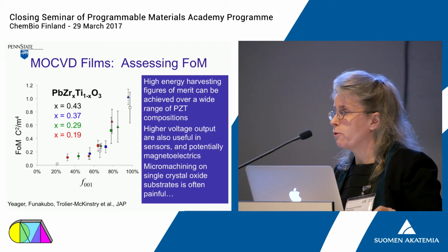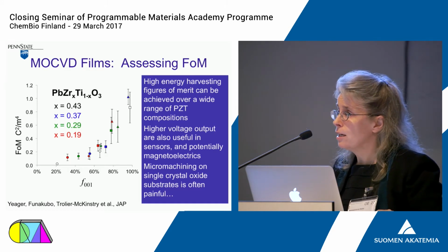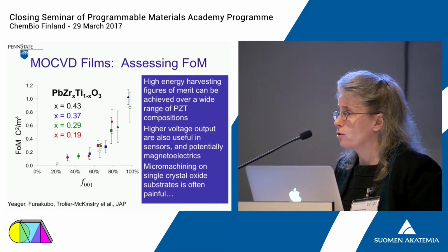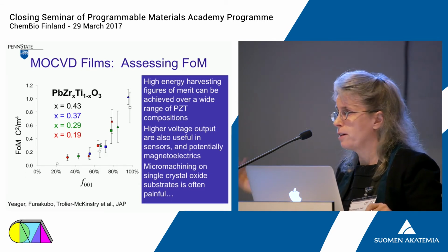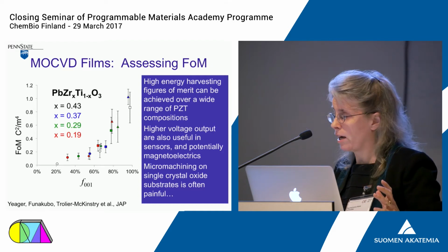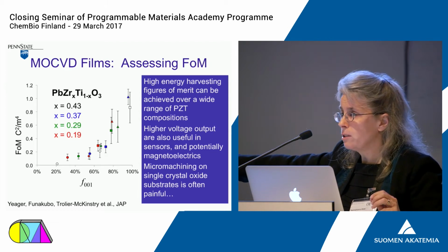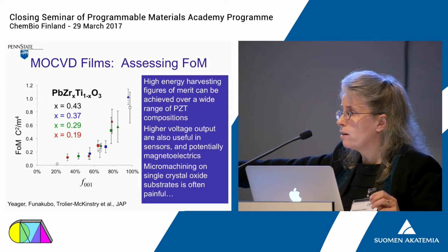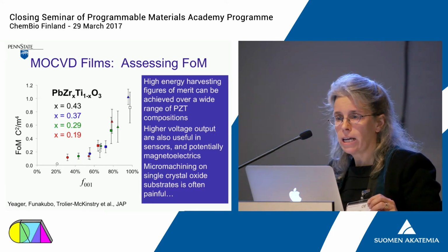So we made wonderful films, and we destroyed actually several generations of wonderful films, trying to turn them into functional harvesters. So we developed a very elaborate protection scheme for the front and the back side of those devices. We finally got some of them to survive. And now we make a thin structure out of a brittle material, hang a heavy weight on the end, and shake it. And hallelujah, crack propagation happens.